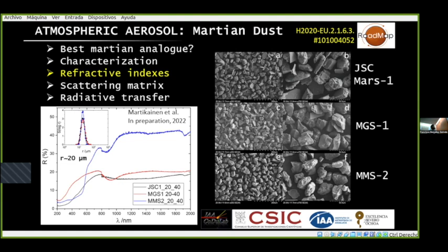And what we have found with our analogs is that they have absorptions which are much lower than the ones that have been commonly assumed in all Martian studies. And in fact, we've taken spectra from the Martian surface. We have reproduced them using the same code and using these new optical indices. And we find that we are able to reproduce the observations very nicely, whereas if you use the old absorption indices, the result is terrible. So this is some encouraging news for us.